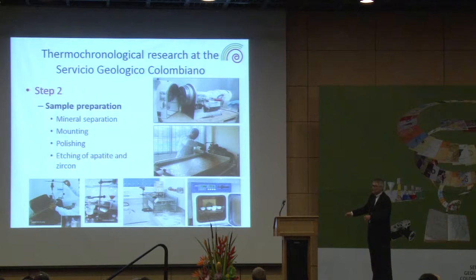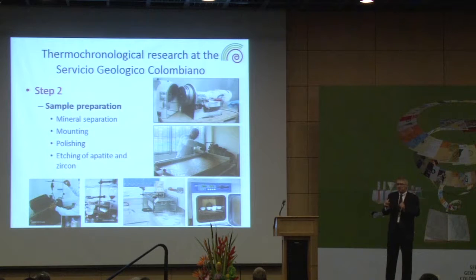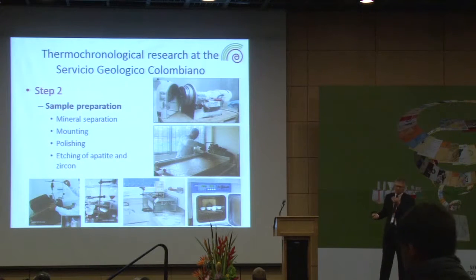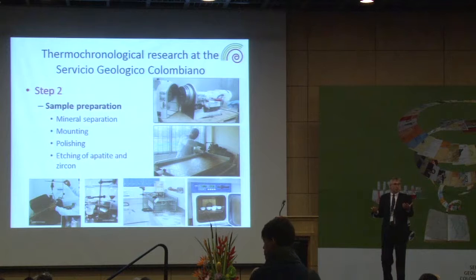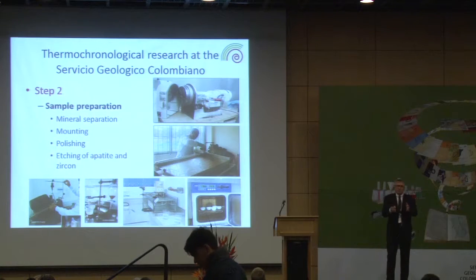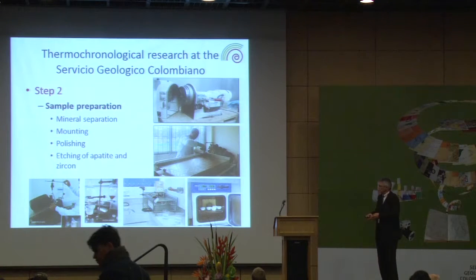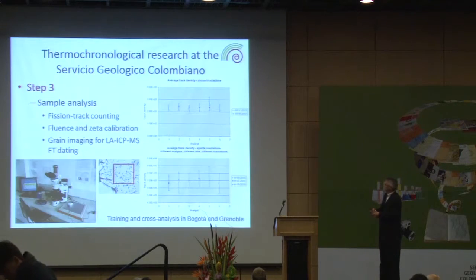The zircon fission track ageing is much more complicated. It needs hours of etching and control of every single sample after each etching step, and they're etched in a solution of sodium potassium hydroxide at about 228 degrees Celsius. And so a little bit of experience is needed, and this is why many fission track labs in the world only use apatites, but we are also doing zircons, which is a very powerful technique.